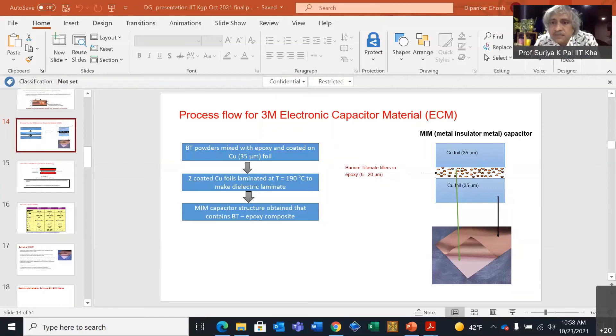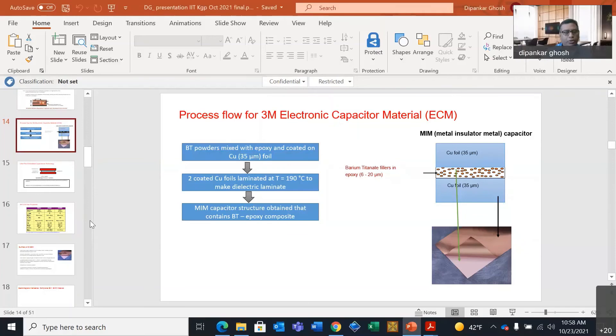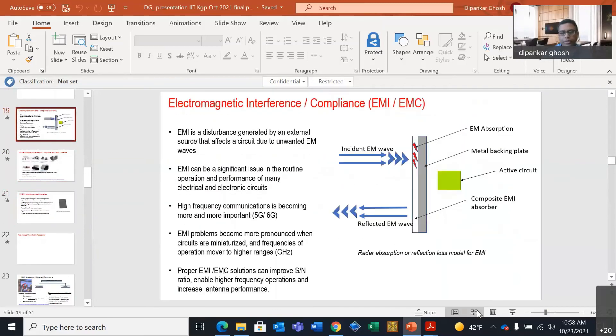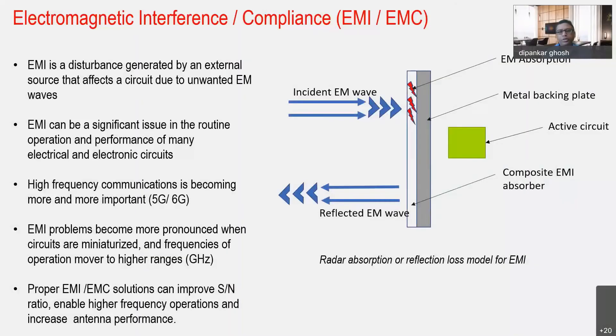There is a question about EMI applications — do you measure S-parameters? Yes. For high-frequency applications, the way we measure permittivity and loss values, and for magnetic materials permeability and loss values, is from S-parameters. We use standard network analyzers and algorithms to get the dielectric constant and magnetic permeability values from those S-parameters.